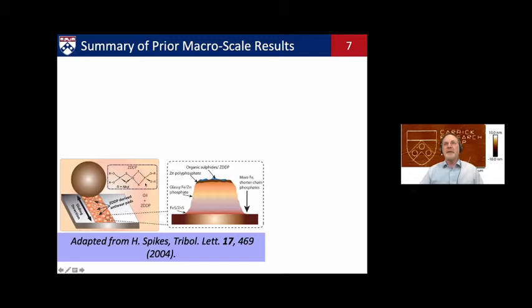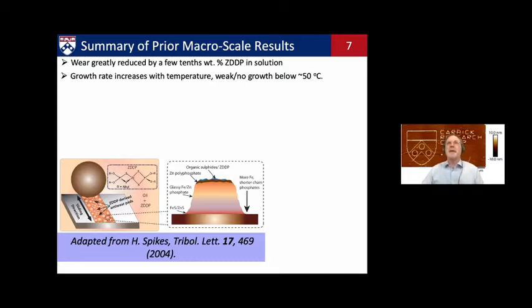So we have been using, well, first let me quickly review what's known about the classic mechanism of ZDDP. And Hugh Spikes has a nice review article from 2004 covering this. We know that wherever you slide, you get these patchy films made from the reaction products of these ZDDP molecular fragments that build up. And by having this protective film on the surface, just a few tenths of a percent of ZDDP in solution will greatly reduce wear of steel and many other materials.